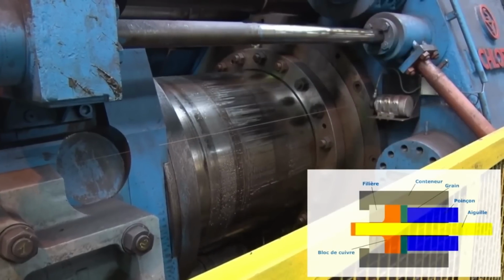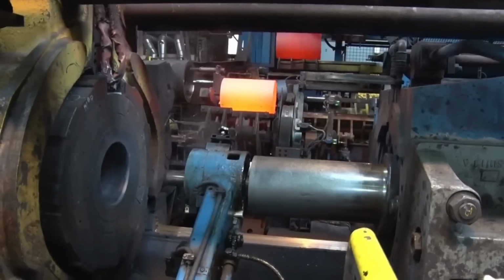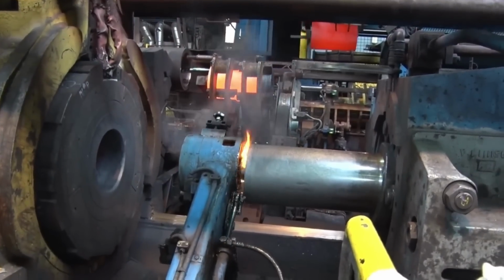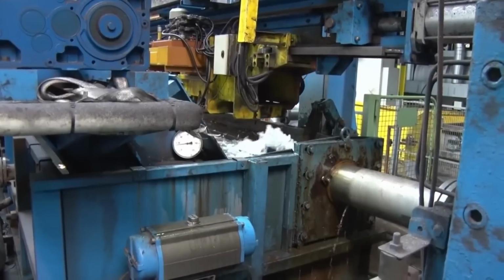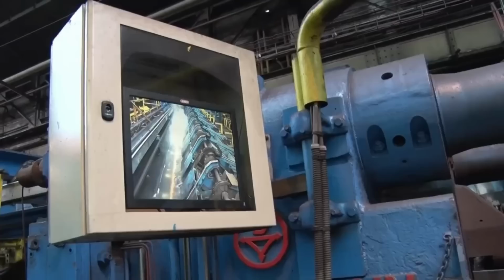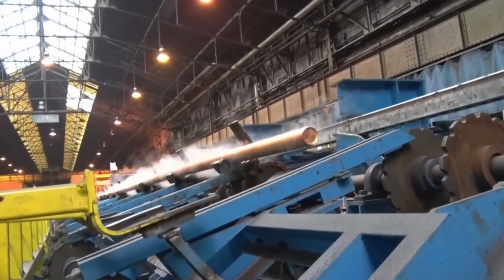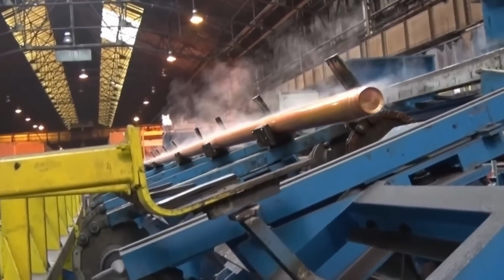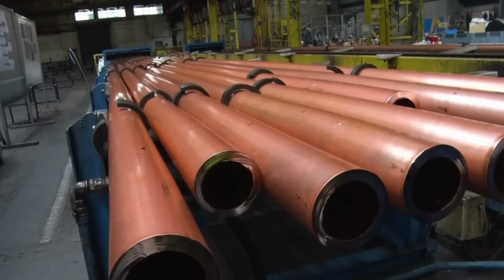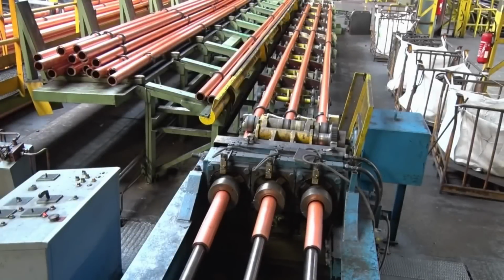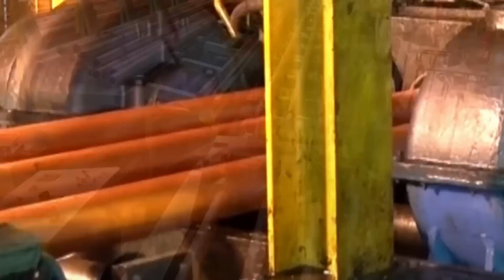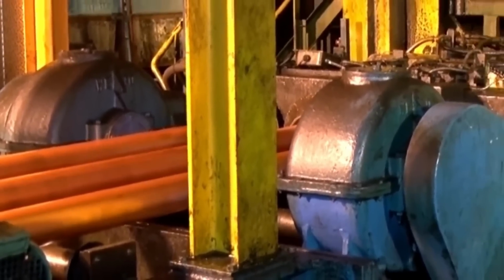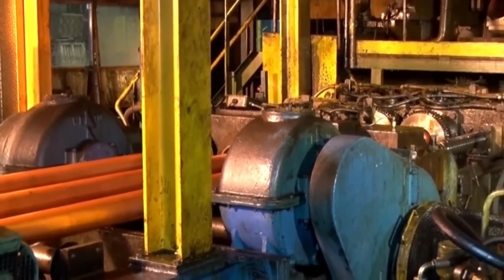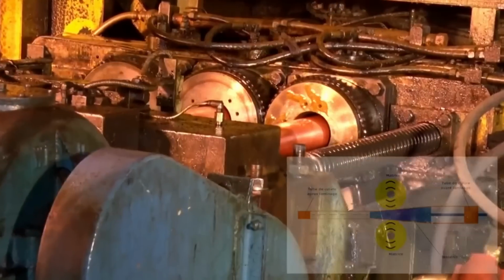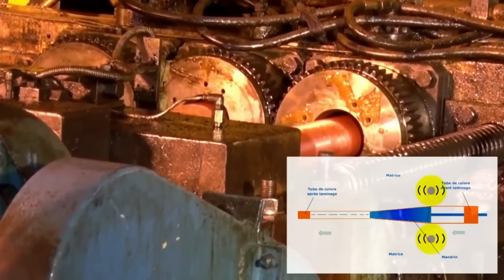Subsequent operations are carried out cold and aim to reduce the diameter and thickness of the tube to achieve the desired final dimensions. Cold rolling is the first step in this process, which involves passing the tube between conical dies and a mandrel. The tube is forced to pass between the dies and the mandrel, resulting in a reduction in diameter and thickness. The length of the tube can exceed 120 meters at this stage. The obtained tube is then coiled in large baskets and stored for further processing.